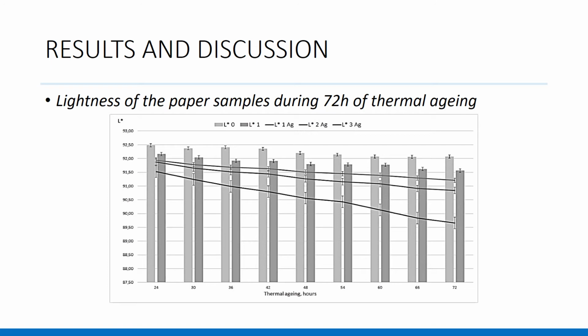The color coordinate L, which expresses the lightness, brightness and the brilliance of the paper, decreases with the silver water treatment. The color parameter variation with time is comparatively low, being most sensitive during the first 24 hours of aging. With increasing consumption of silver water and duration of the thermal aging, the color of the paper samples is getting darker and the color difference is getting bigger. At 3 milliliter silver water treatment, the lightness of the paper samples significantly decreases.